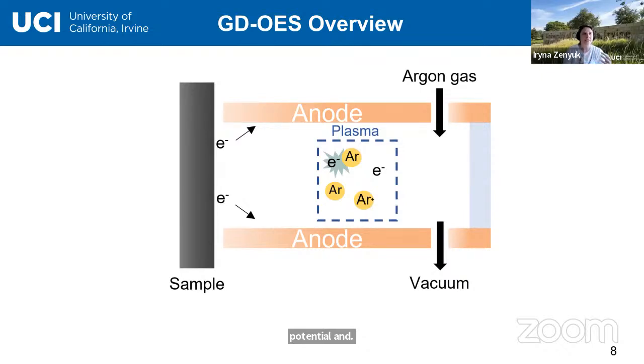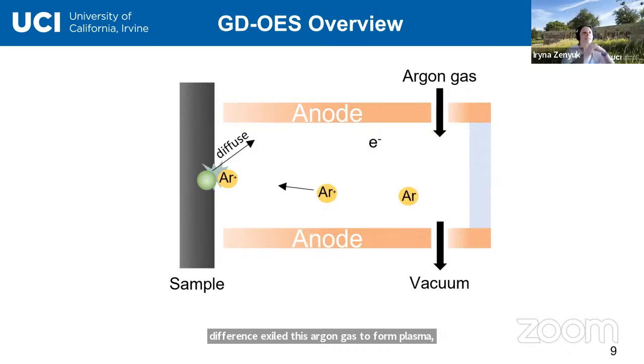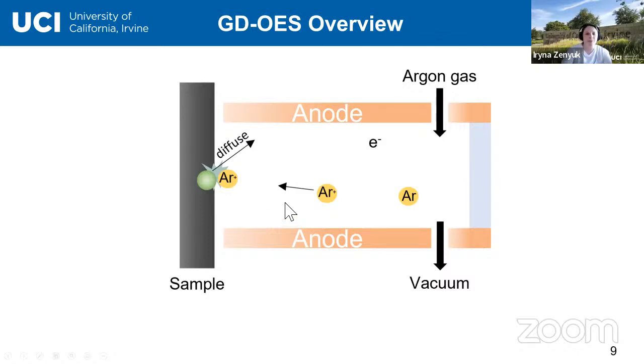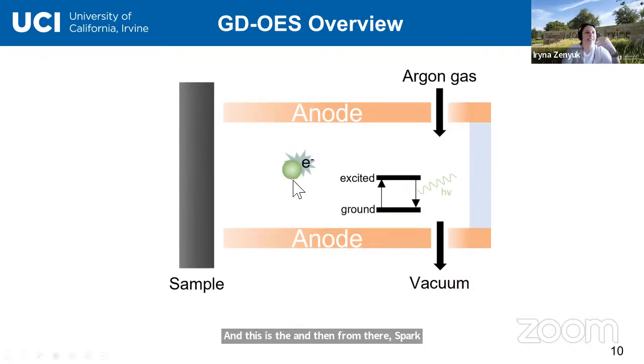Electrons that are accelerated by the potential difference excite this argon gas to form plasma, consisting of positive ions, neutral particles, and free electrons. In the next step, the positive ions of the plasma are attracted to the negative electrode. They have sufficient energy to knock atoms off the surface. That's how we sputter away the sample. Then the sputtered atoms are excited by collisions with free electrons in the plasma, and as these elements de-excite, they emit light at certain characteristic wavelengths.